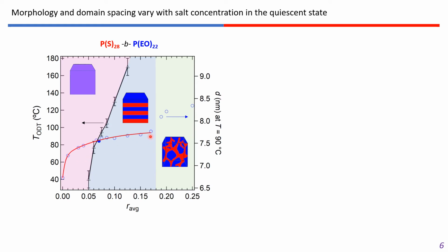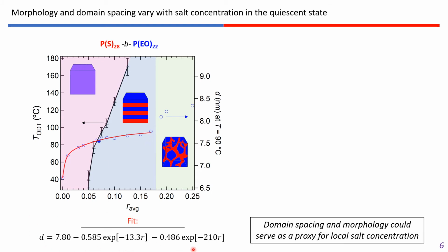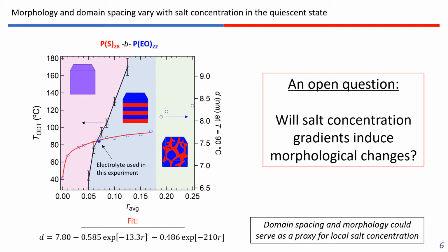We see that in this region, it follows a predictable trend, which we can fit to this double exponential function in order to obtain a relationship for the domain spacing as a function of salt concentration. This implies that we might be able to use the domain spacing and morphology as a proxy for the local salt concentration in the cell. In particular, we pick one salt concentration to use for this experiment, which is shown as a filled circle and is near the disorder to order phase boundary. An open question is whether or not this current-induced salt concentration gradient will result in morphological changes in the block copolymer.